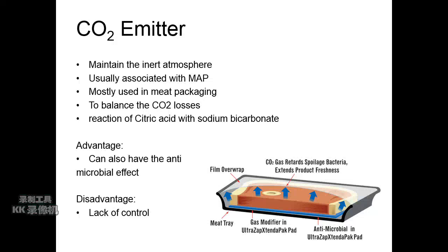The emission of carbon dioxide is triggered by the drip loss from the meat absorbed into the emitter pad, and the water reacts with the citric acid and sodium bicarbonate present in the pad, generating carbon dioxide through the reaction. The advantage of this kind of material is that it can also have an antimicrobial effect, but the problem is that controlling the emission of carbon dioxide is not very ideal.